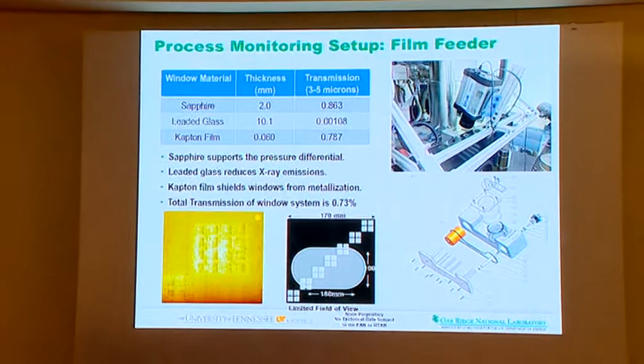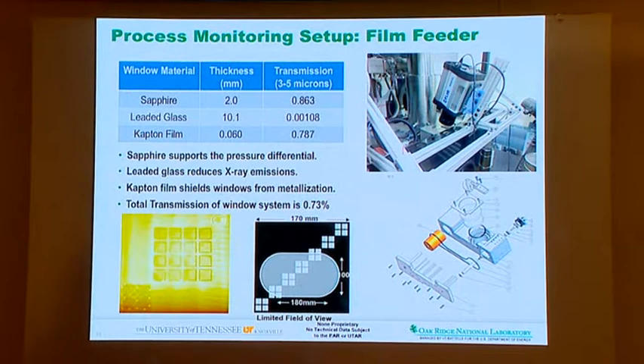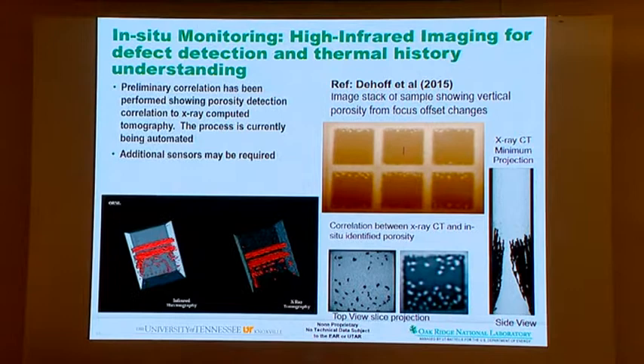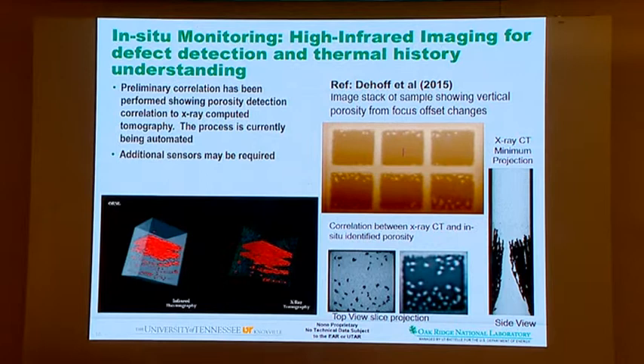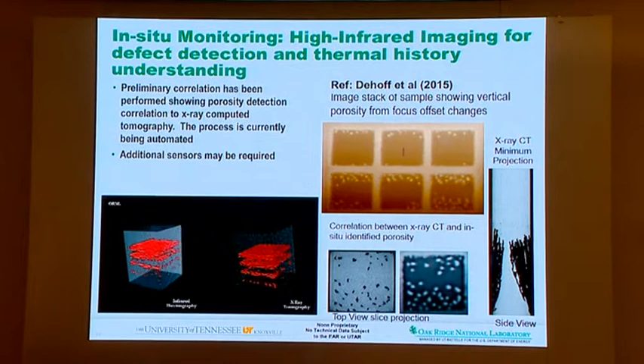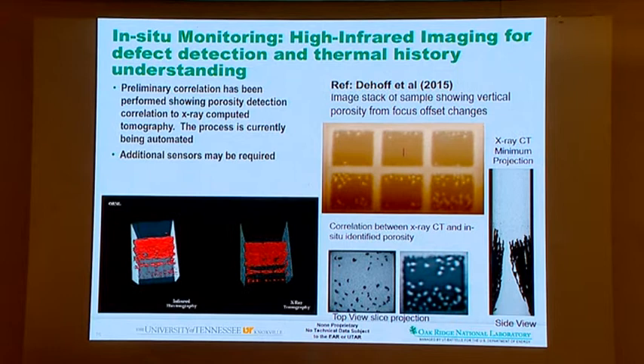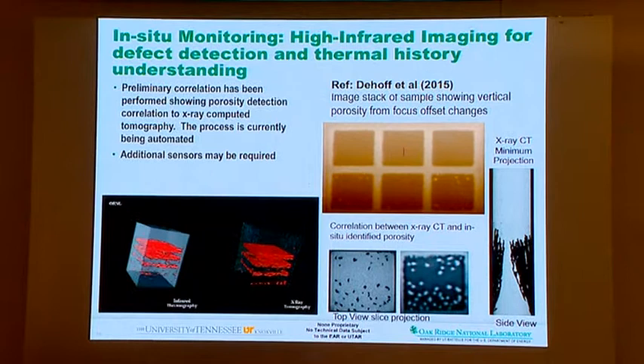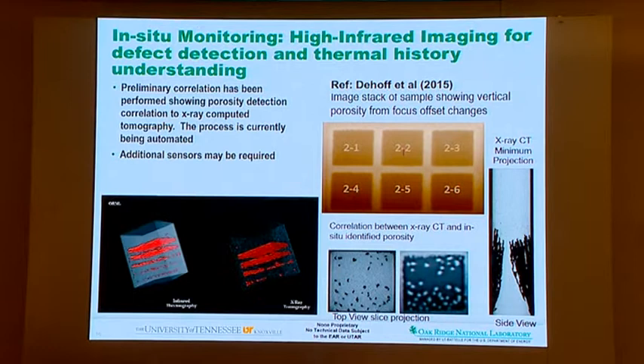So now we have a thermal signature. So what? We can use the thermal signature to figure out whether you are going to create porosity in that location or not. You can develop an algorithm, and using the thermal imaging, you can say that at that location you will have a porosity. That is what's shown on your left-hand side video. That's actually a three-dimensional voxel imaging of the tendency for forming porosity.